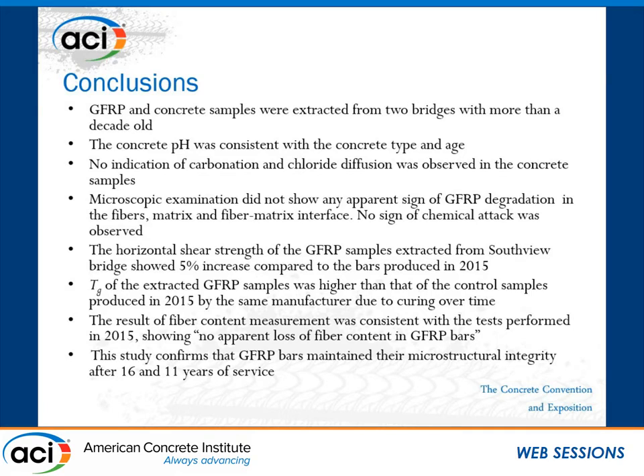In terms of mechanical properties, the horizontal shear strength showed a 5% increase compared to the benchmark values, and the same was the case for the glass transition temperature. Also, the fiber content was in the exact expected range.